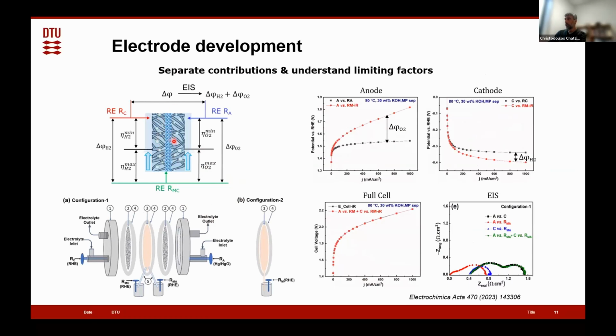Here you see the diaphragm and the two electrodes. We're placing a reference electrode right in the middle of the diaphragm, as well as two reference electrodes behind each electrode. And this allows us to actually separate the contributions from the anode and the cathode, as well as measure how much losses one has within each electrode for transport of ions through the depth of the electrode. So this allows us to understand better how each electrode architecture influences the electrode performance.